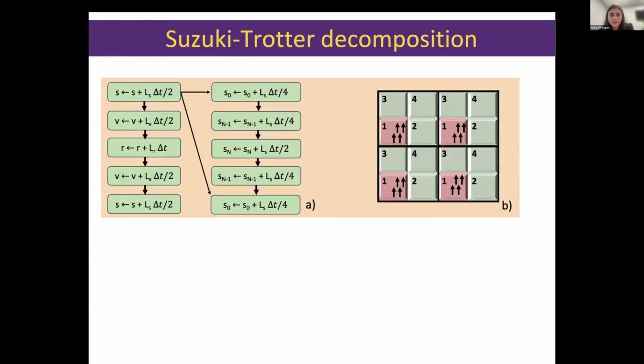We're using something called the Suzuki-Trotter decomposition. We want our system to conserve energy and angular momentum, so we need to go through this more sophisticated numerical scheme, in which we do an update for the spin, velocity, position, velocity, and spin. This is a second order Suzuki-Trotter decomposition, and we do another decomposition on the spin since the spins interact via the effective field. So indeed, for this type of spin lattice simulation, we need to look into more complicated integration schemes.